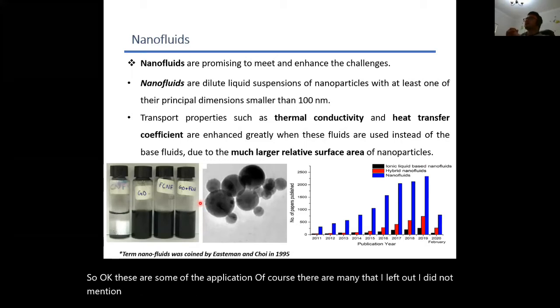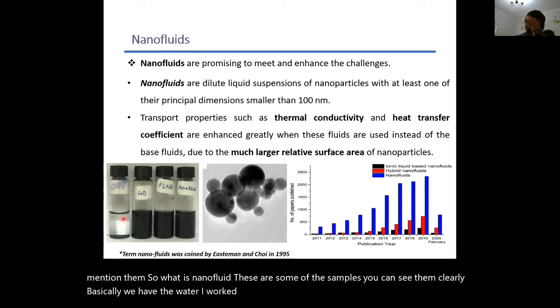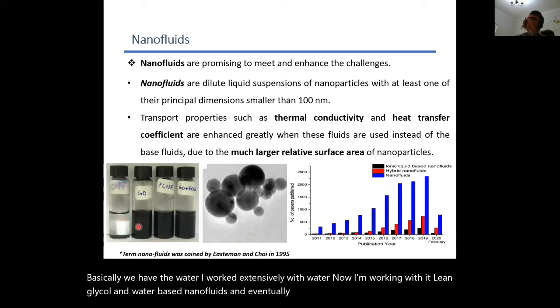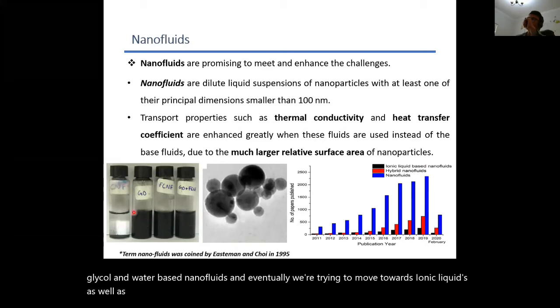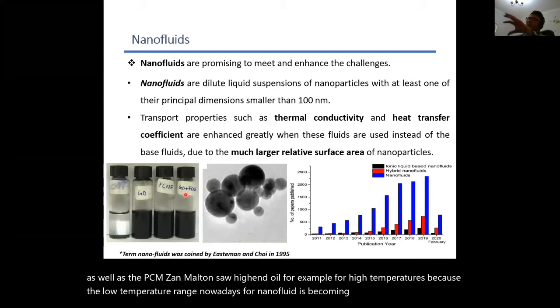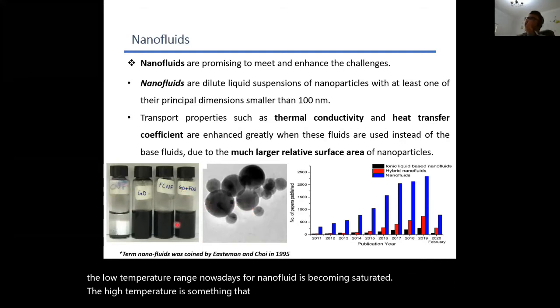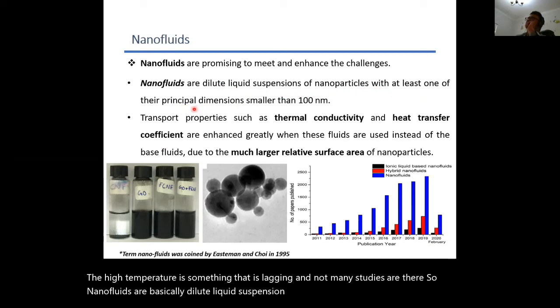So what is nanofluid? These are some of the samples. You can see them clearly. Basically, we have water. I worked extensively with water. Now I'm working with ethylene glycol and water-based nanofluids. And eventually, we are trying to move towards ionic liquids as well as PCMs and molten salts, for example, for high temperatures. Because the low temperature range for nanofluids is becoming saturated. The high temperature is something that is lagging, and not many studies are there. So nanofluids are basically dilute liquid suspensions of nanoparticles with at least one of their principal dimensions smaller than 100 nanometers.